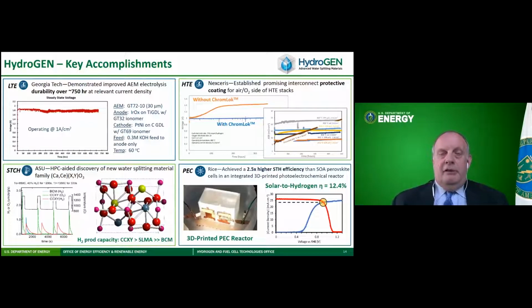Some of the recent accomplishments: in the area of alkaline exchange membrane electrolysis, one of the issues there has been the durability of the membranes, and work at Georgia Tech, one of the Seedling projects, has been able to demonstrate very stable performance for over 750 hours under relevant operating conditions. So this is an exciting new development where we're getting good stable performance over a long period of time.